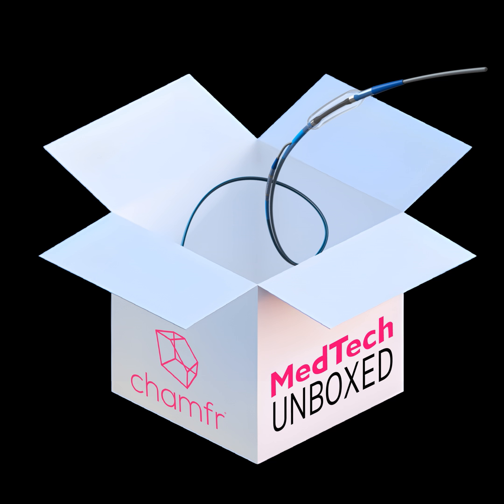PEEK needs a little help with that, because the other contending challenge of PEEK is that it is quite easy flowing and will flow into very small crevices. So it results in flash. Anywhere you have a match line on a part, the main parting line between the two mold halves, anywhere you maybe have a core pin or a side core feature, where there's a match line between two different pieces of steel, PEEK is very prone to trying to squeeze its way into those little crevices, which are the same little crevices that act as your vents.